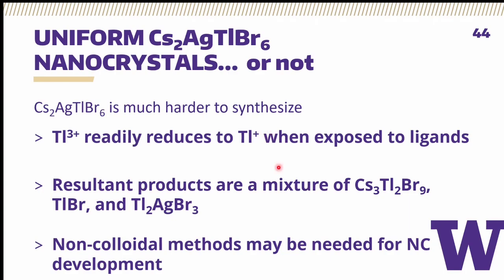Even when this amine is replaced or eliminated to just get basic powders, the resultant products are usually the 3,2,9 motif of the cesium silver thallium bromide, as well as, even without the amine, a bunch of 1+ contaminant products like thallium bromide and thallium silver bromide. So some other way of making nanocrystals, some tricks with thermodynamics and kinetics, and potentially even non-colloidal methods, like a microwave method of some kind that no one has used in perovskites before, are going to be needed if someone wants to really use this material in PV devices or in CdTe tandems.